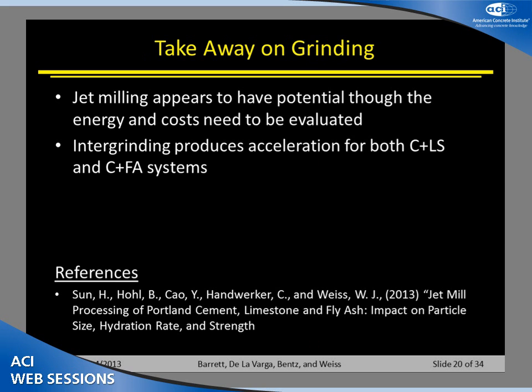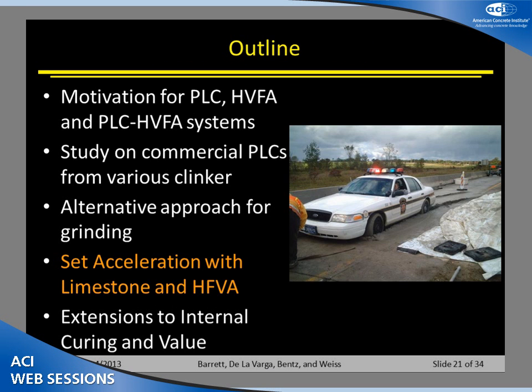So the jet mill appears to have some potential promise, although we really need to look a little bit more at the energy and costs and what it takes to really scale that up. But the real benefit of this is that by intergrinding, we can accelerate both limestone and the fly ash, and there's a potential here to start reclaiming some of that ash that's been ponded, because all of a sudden we can get it reactivated because we're crushing it and getting that material to start to come out.